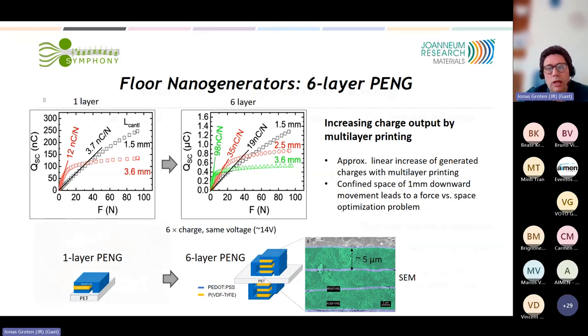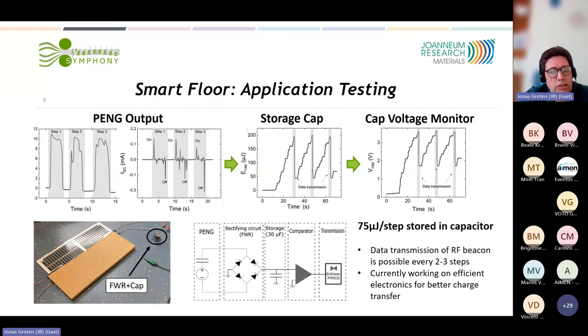cantilever example. And we finally managed to build up such a floor so that with each step, we have at the nanogenerator an open circuit voltage of 10 volts and current peaks of around 150 microamps. And with a very simple circuit, we stored this basically in a capacitor and charged up a 30 microfarad capacitor. And as soon as we have reached 3.6 volt, a comparator switches through and powers a small IoT device to transmit an RF beacon. So this is possible within two to three steps.